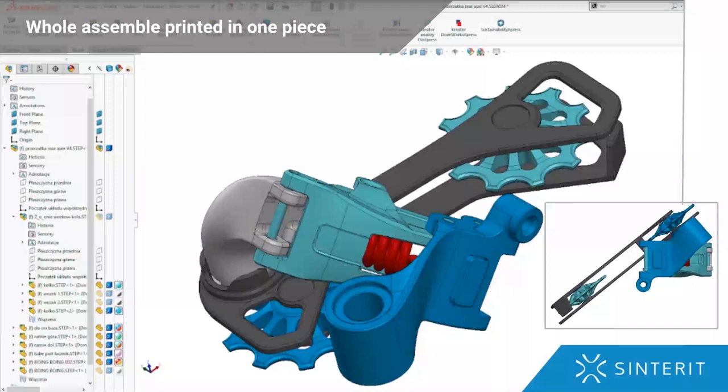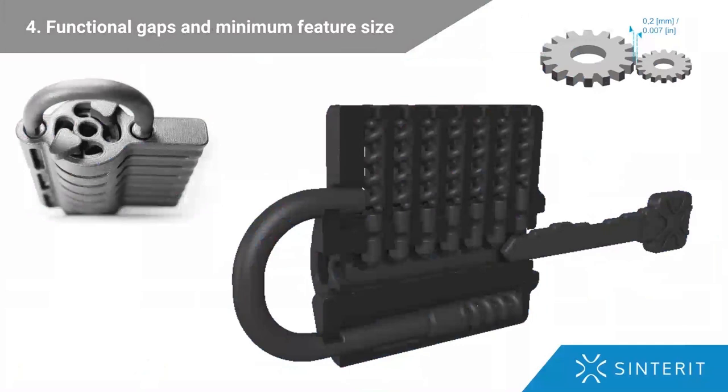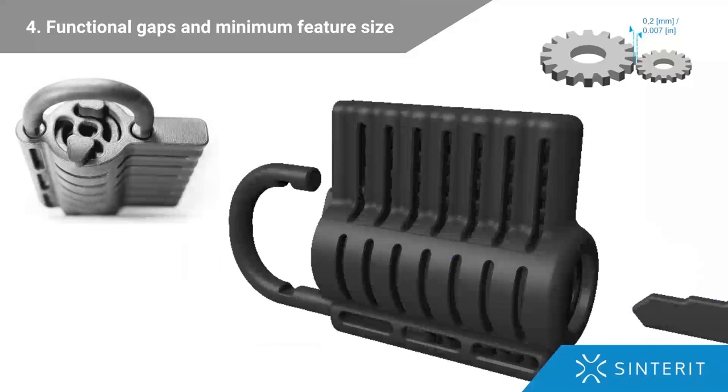However, if you want to do so, you'll need to leave enough space between the joints surfaces. And it has to be considered when you are creating designs, because if you don't do that, then the joints won't rotate or they won't move. So the absolute minimal clearance is 0.2 millimeters. But we actually recommend a bit more, especially in case of 3D printing beginners.